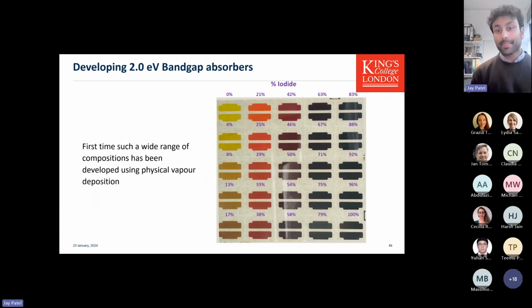I've shown that I use this facility to develop all these different compositions of perovskite in one run. That's fantastic. Now it's cut my workload in this particular case by 25 times. Previously, I would have had to put in the substrate each time and fabricate each of these materials in a single deposition. Now you can do them all in one go.